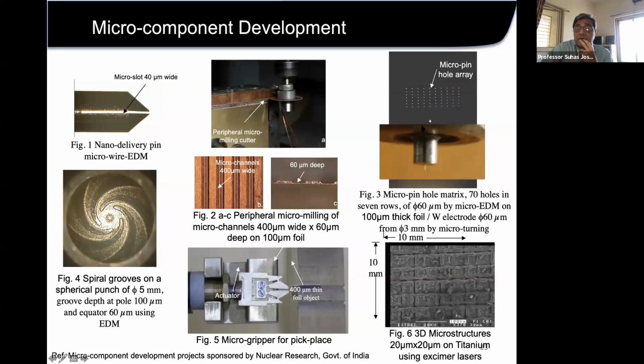So this is another component where we have a very, very fine electrode of about 60 micrometer. And this was machined by turning initially, and that 60 micrometer electrode was used in situ to make the holes of 60 micrometer size on a foil. So once the electrode is done, we don't go to turning operation, but we just go to EDM operation and we perform the EDM. So this is again a spiral groove, which is another kind of component. These are very, very fine kind of grooves made by EDM process to give a differential pressure. So these are spiral grooves, and when they rotate, they create a differential pressure across these grooves.